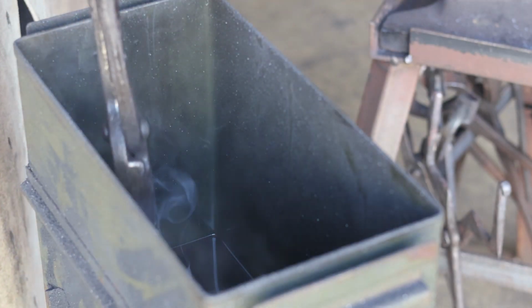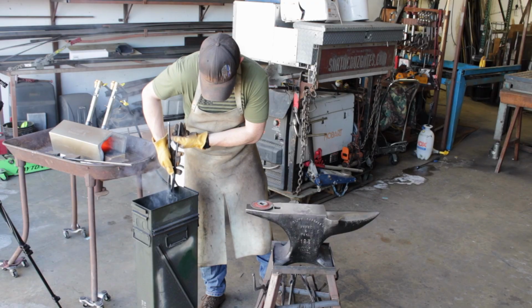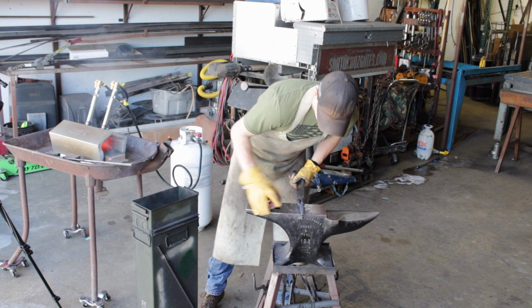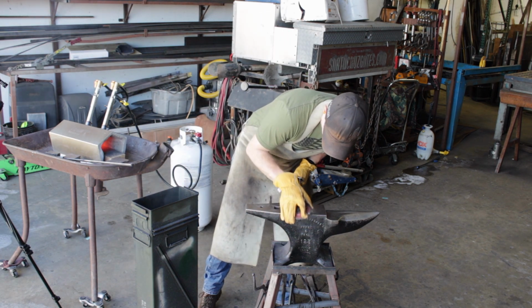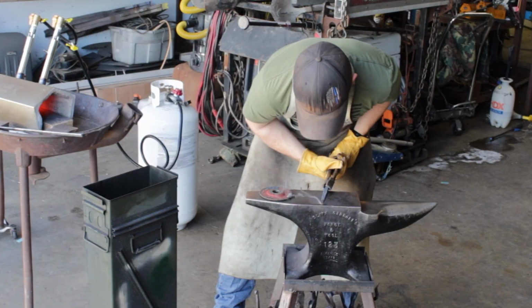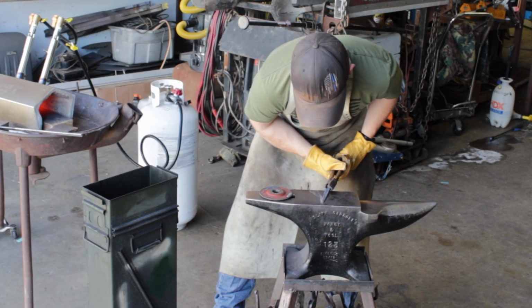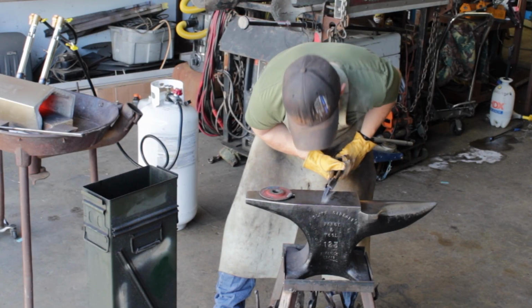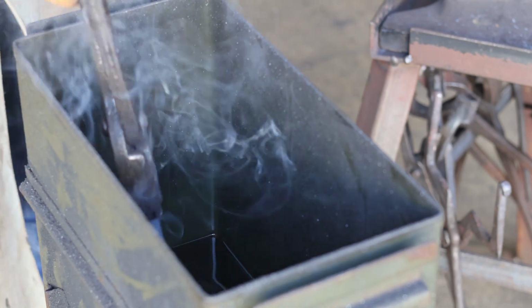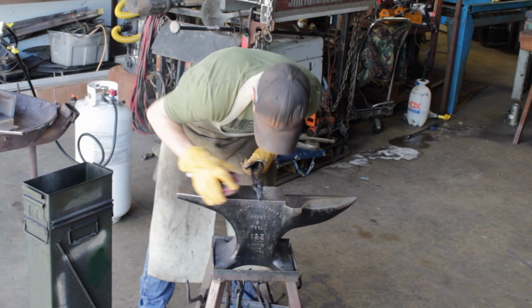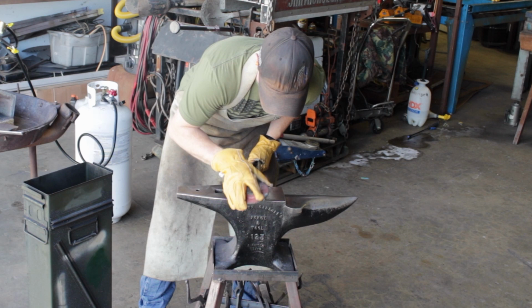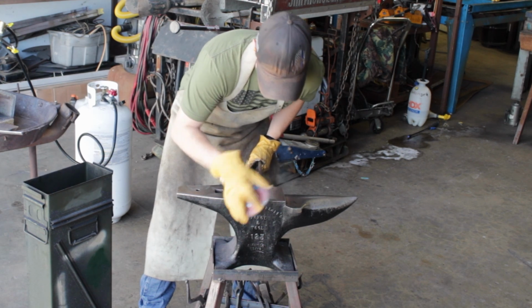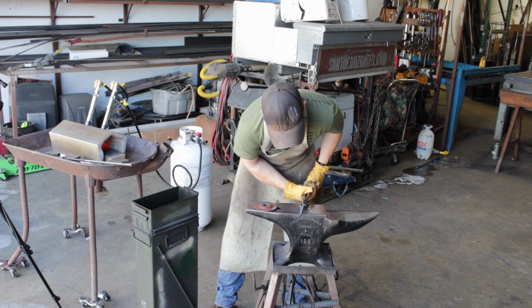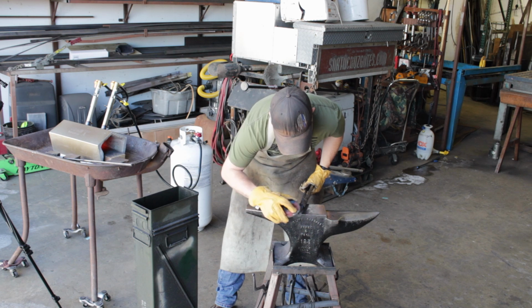Too much. Now I'm looking for a dull yellow color, a dull straw color. That's going to indicate about 400 to 450 degrees. And then I quench it again to keep it from heating up further. I'm going to do that as many times as I can until it stops changing colors.